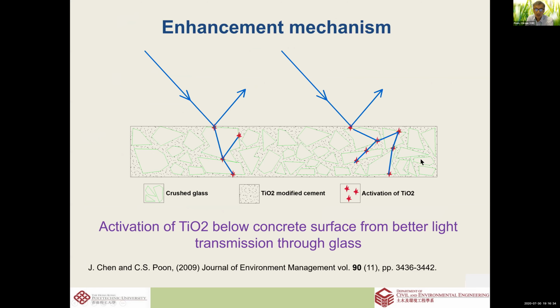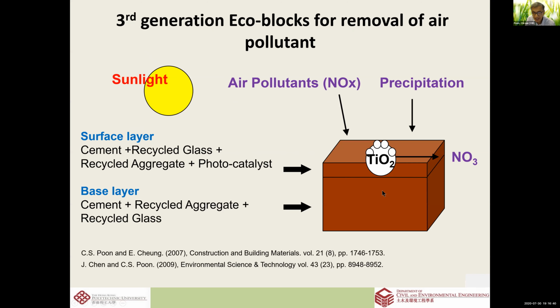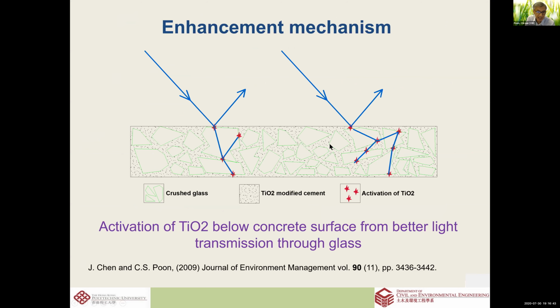In our development, we put glass on the surface layer as well. The glass is 5 mm, and we put in particularly clear glass. The glass actually allows the penetration of sunlight into deeper parts of the surface. When we have TiO2 only on the very top surface, the area that could be in contact with the air pollutant is quite limited. But some TiO2 is embedded underneath the very top surface.